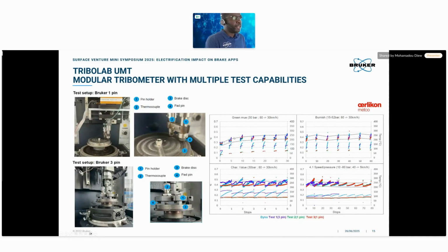But with an error, or deviation, of something like 10% on each of these tests, you can see that the blue line on the friction is in the same range for the dyno, the test with 1-pin, and the test with 3-pin. This will be the same even on the burnish, the characteristic value and the speed pressure. You will find exactly the same tendency.